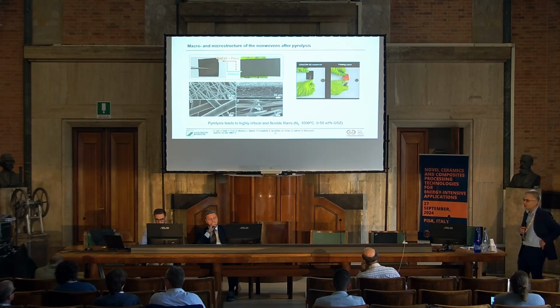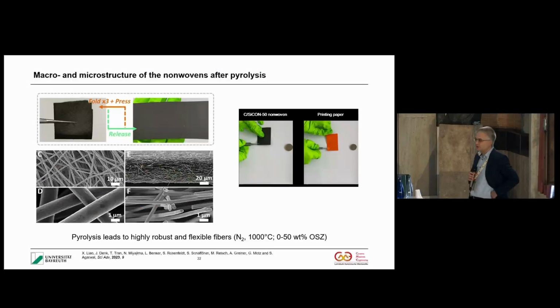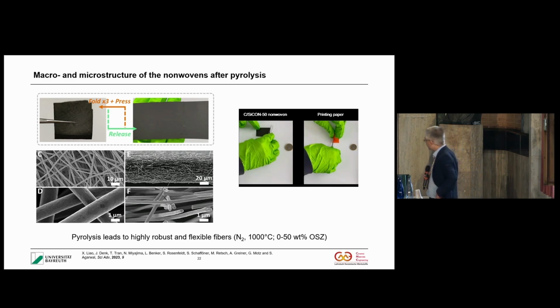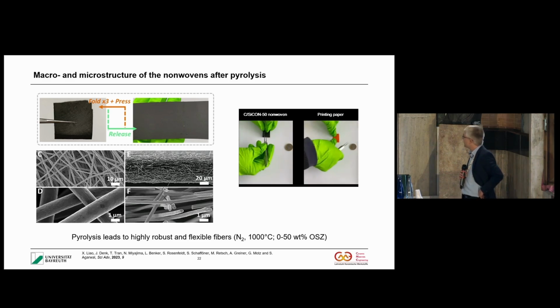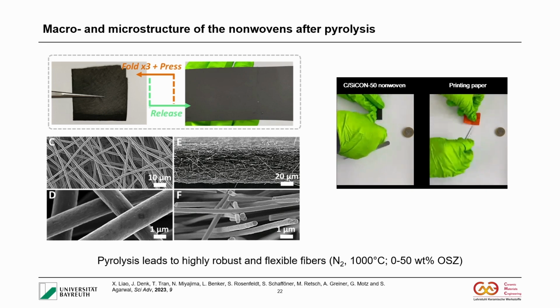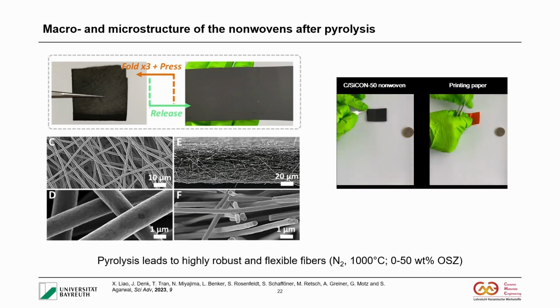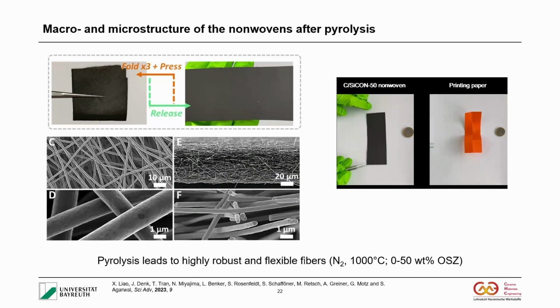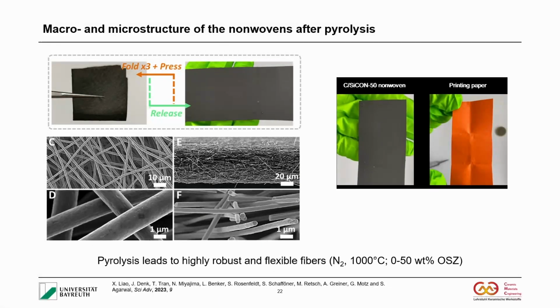I think it's the same PhD students. It's not a competition between two PhD students who has the better foldability. So we have on the right side the printing paper, and on the left side the non-woven after pyrolysis. It was probably not performed in our lab because we have other gloves. So it was the chemistry lab. So for example, this is the printing paper and this is the non-woven, and there was not much difference even. And for example, the image F here is also showing the fibers after folding, so there was no breakage of the fibers observed.